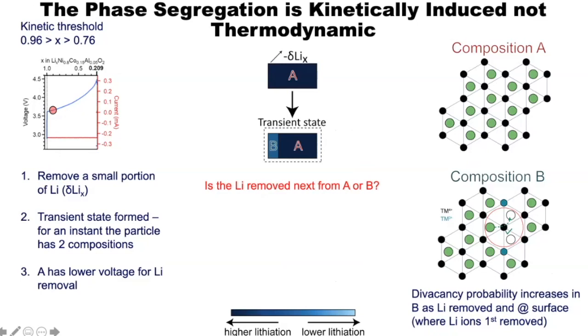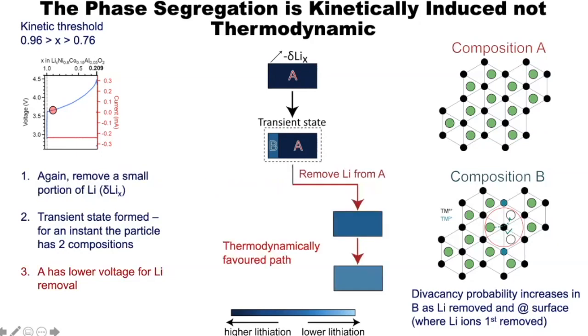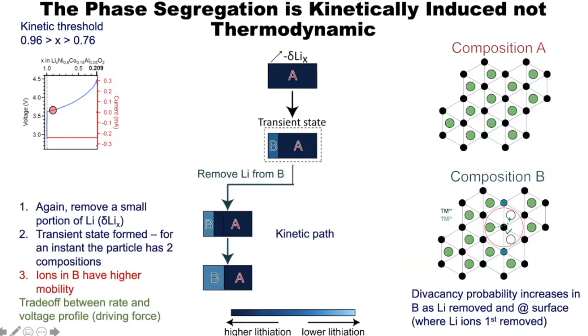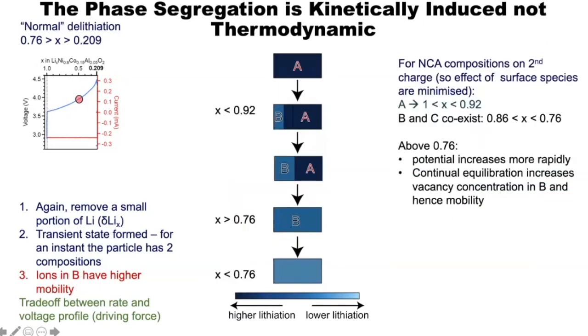So you can then imagine, or do a thought experiment, where you pull a little bit of the lithium out of the surface of the material. And this is to form phase B. So you have composition A that's almost completely stuffed with lithium, composition B that's partially delithiated. And then you can ask the question, where does the next lithium come from? Are you going to pull it out of phase A, which would be the thermodynamic pathway, or, because of the difficulties of the kinetics of pulling it out of phase A, where you have very reduced lithium mobility, what the diffraction suggests is that you go via a kinetic pathway where it's preferable to pull the lithium out of phase B because it's just easier, because you have much more rapid lithium mobility in this phase. And so what you see then, at least in the first part of the delithiation, is this removal of the lithium by this two-phase behavior.